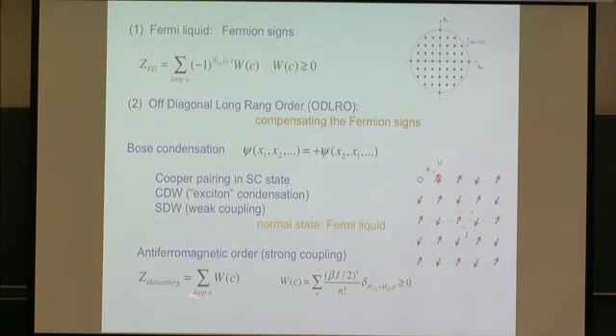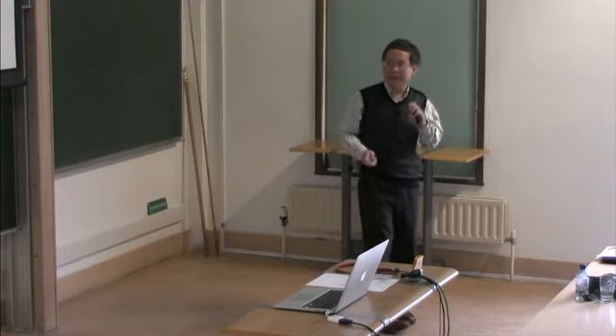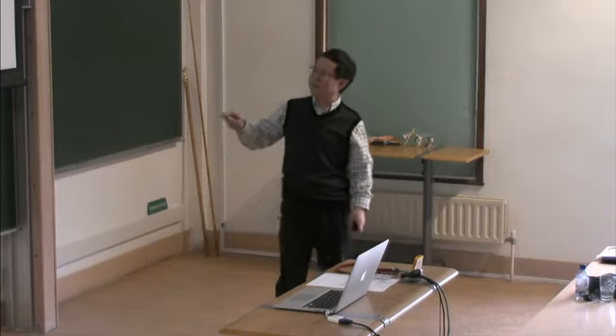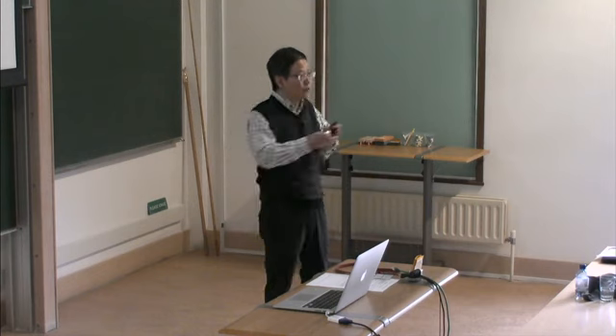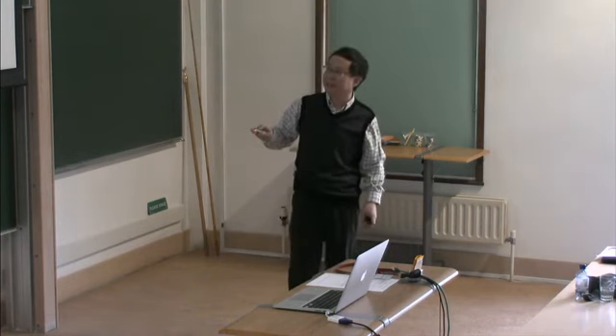In this case, if you write down the partition function, what you see is that all these paths actually become positive weight, without sign. The fermion sign totally disappears here. So you see that at low temperature, this localized spin will demonstrate long-range antiferromagnetic ordering, just like a spin-density-wave case.